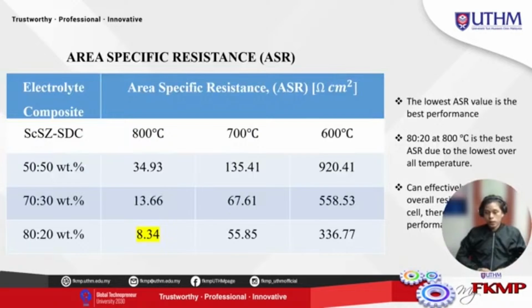From the EIS testing, we can calculate the area specific resistance. The lowest ASR value is the best performance, and the result shows 80-20 at 800 degrees Celsius is the best ASR value because it has the lowest ASR over all temperatures. It can effectively reduce the overall resistance in the fuel cell, thereby improving its performance.